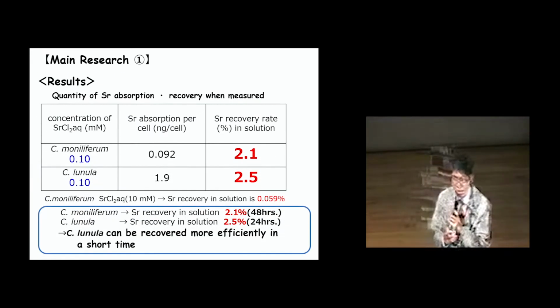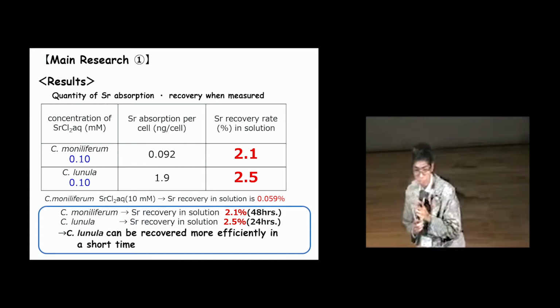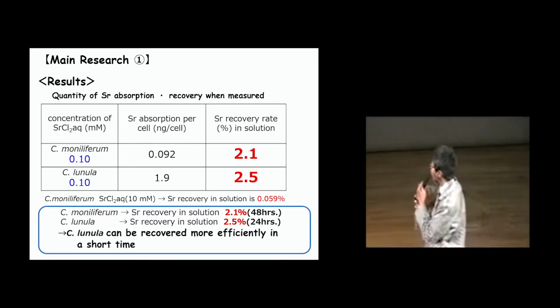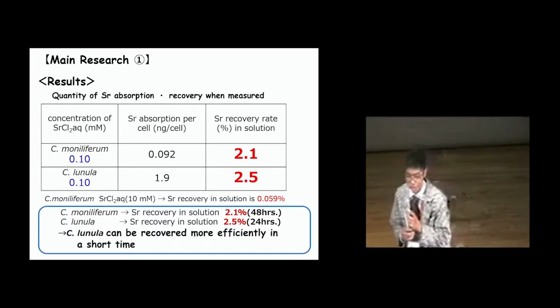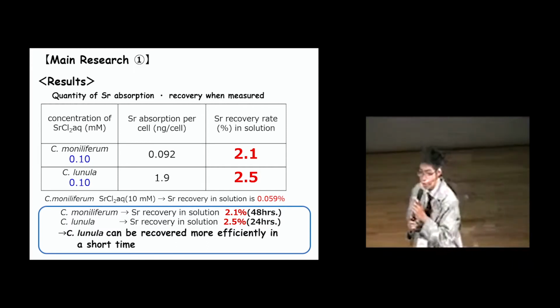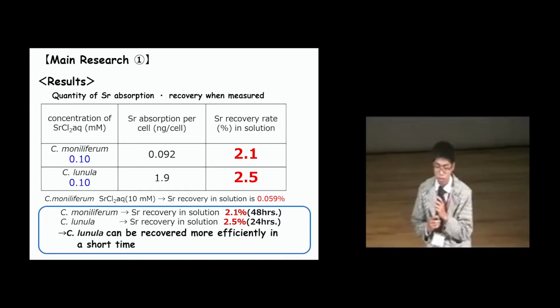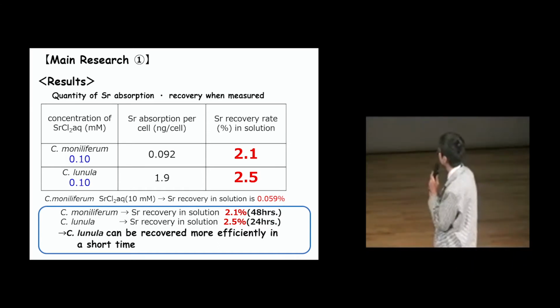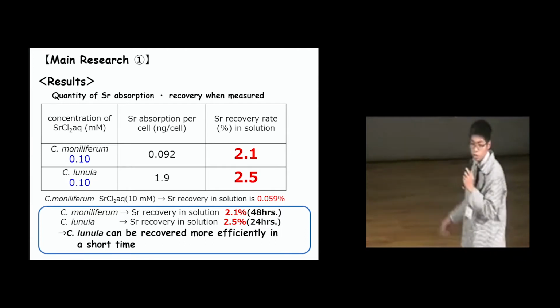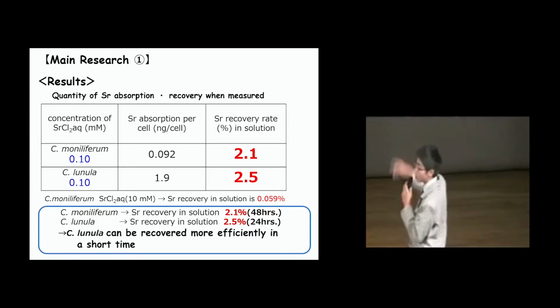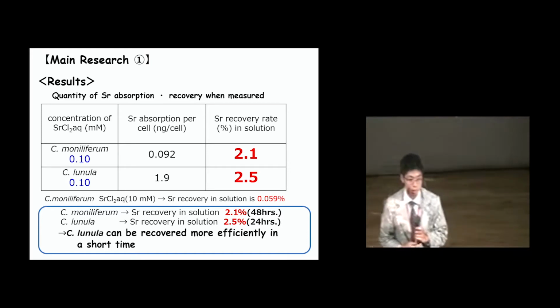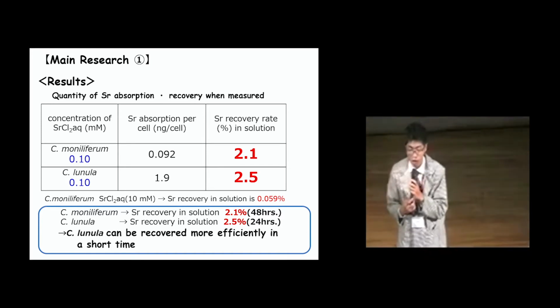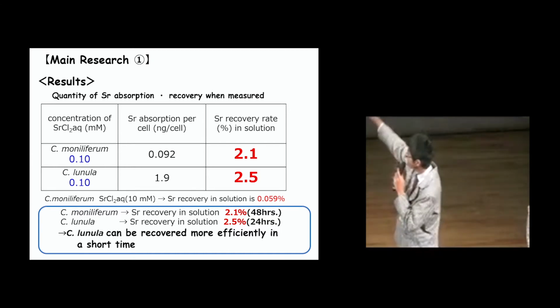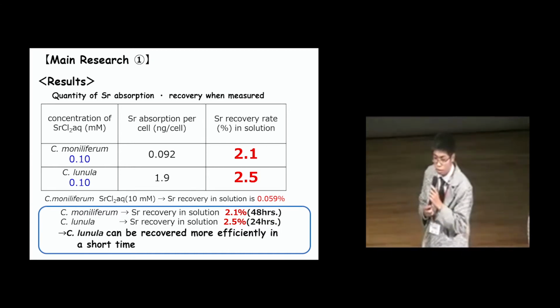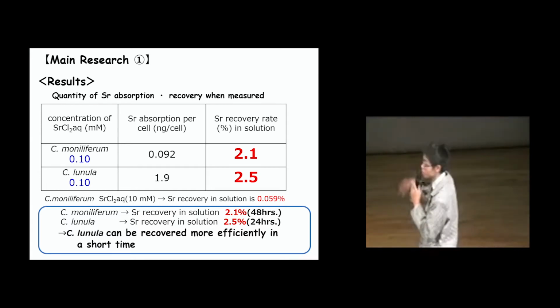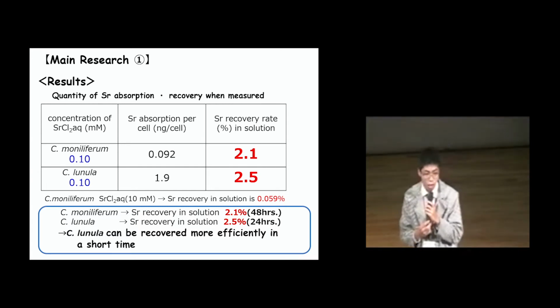Main research one result. Strontium was confirmed from the cell. Also, the strontium recovery rate in each solution is 2.1% for Closterium moniliferum and 2.5% for Closterium lunula. Closterium lunula collects strontium in a shorter time than Closterium moniliferum, and it's considered that it is suitable for efficient recovery of strontium.